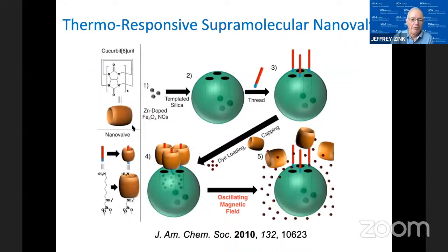For our supramolecular systems, very, very early on, we used this particular type of thread cyclic molecule motif again. In this particular case, the cyclic molecule is cucurbituril, and the thread was this diamine system that's shown on the lower left. And this particular capping is, of course, thermosensitive. The binding is pretty good at lower temperatures, but as you heat it up, you get a bond breaking. And indeed, that works. The cap comes off, and we could release drugs.